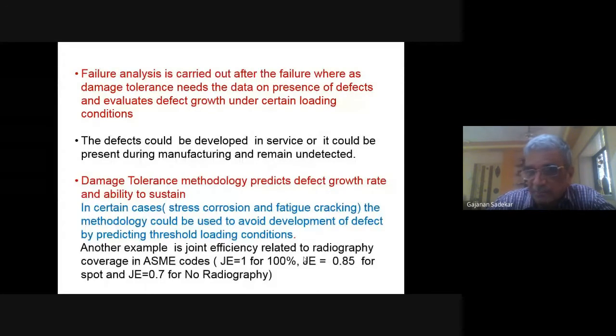In corrosion, for example, somebody can say, okay, you maintain your chloride contents at this level, and then you will not have cracks developing because stress corrosion cracking will not occur. But somebody will say, oh, that has been developed based on corrosion studies. May not be. It's a combination of damage tolerance and corrosion studies, because stress is the parameter which was causing that stress corrosion cracking or the fatigue cracking. So the important thing is to understand that this damage tolerance methodology has a role to play in everything.